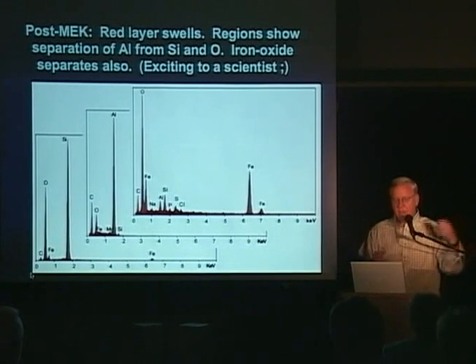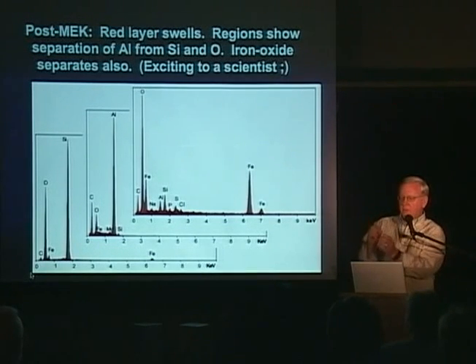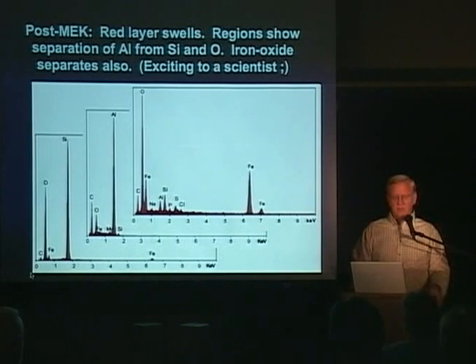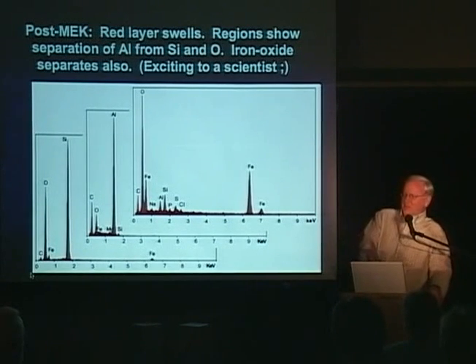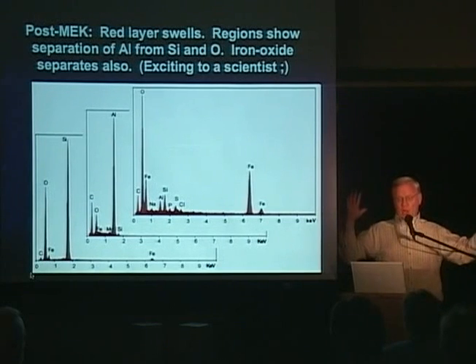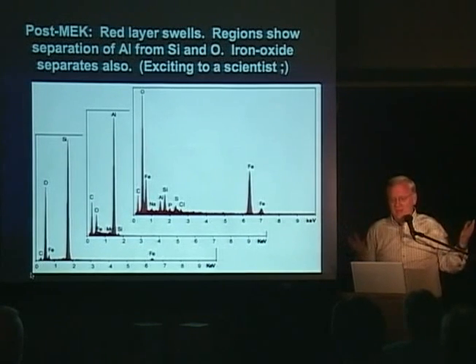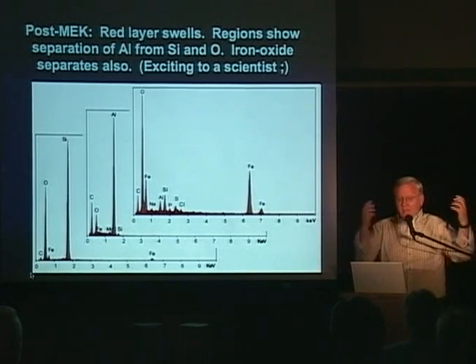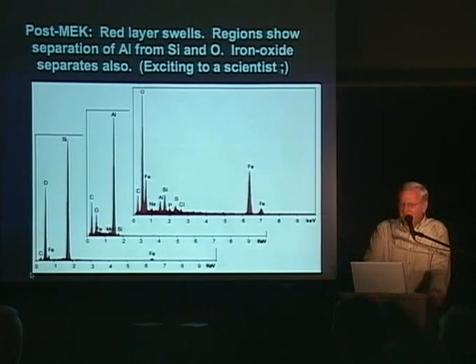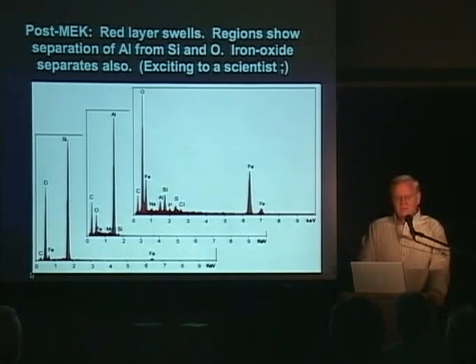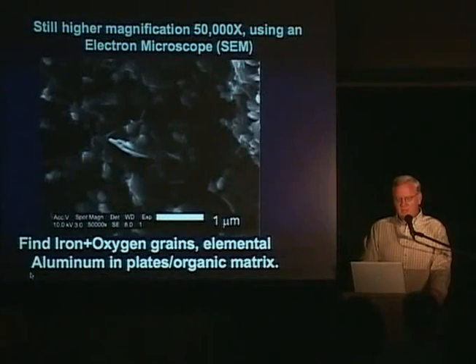Some of it, at least, was elemental. You have little bits of aluminum, little particles of aluminum. You get an oxide layer that forms very rapidly. It's called passivation, and that occurs on the surface and actually protects the interior aluminum from being further oxidized. Sorry, science. To me, this is exciting. You look at that and you say, whoa, there's aluminum in there, elemental aluminum. It's not aluminosilicate because the silicon's separate, and there's iron oxide. This is not just elemental iron. We didn't find any evidence of that in the red material. So now we go on.